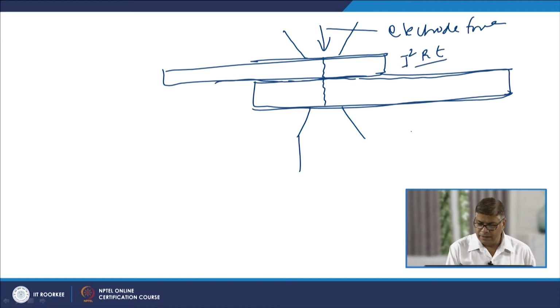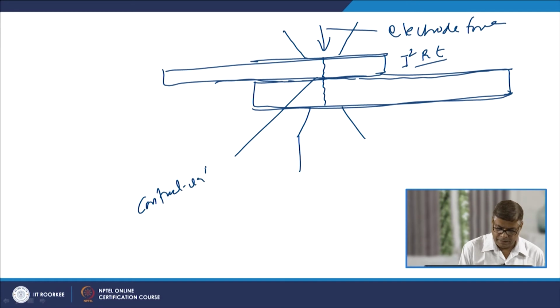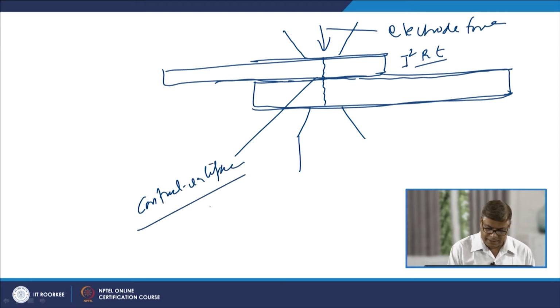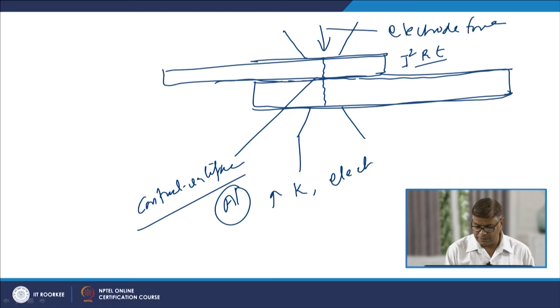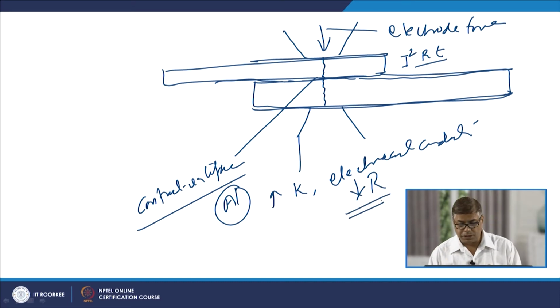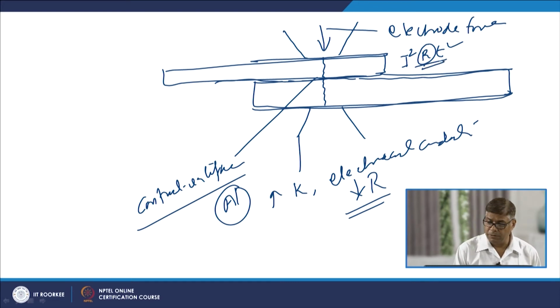But in this case, at the contact interface on both sides we have aluminum, which has higher thermal conductivity and high electrical conductivity, which means electrical resistance is low. So, if we compare with the bare sheets where there is no coating of aluminum, in the case of aluminized steels the R value at the interface will be low, and that is why the heat generated under identical conditions of current and time will be lower because of the lower resistance value.